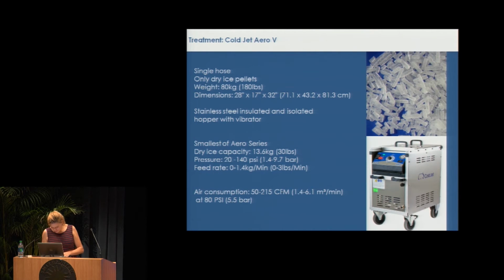There's some other specific things about this machine, and that's that it has a vibration of the hopper, because dry ice pellets tend to clog. If you leave them too long in the sun, they become like one big hard block. So you have to shake them, and there's an internal shaker that keeps the pellets from clogging together.